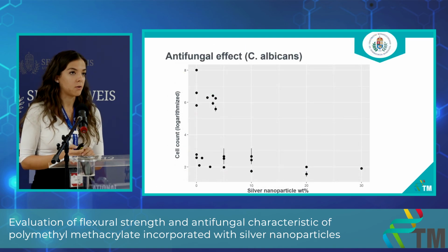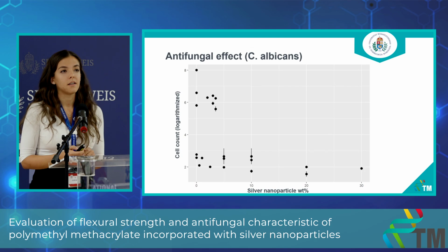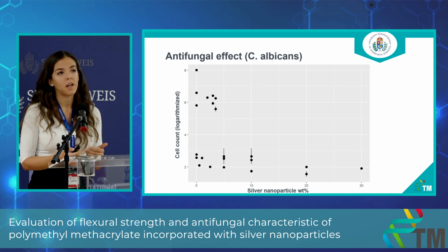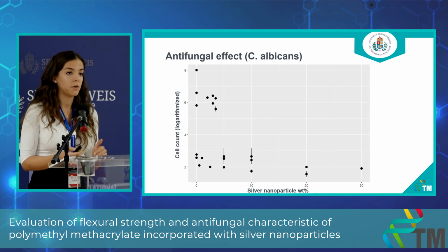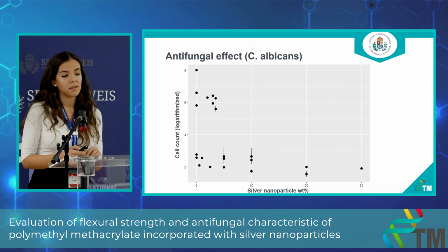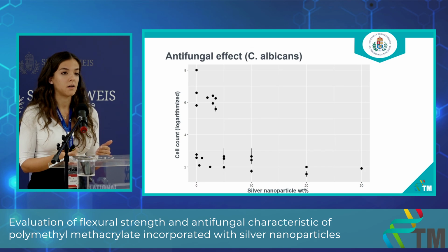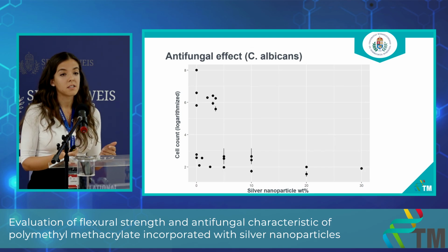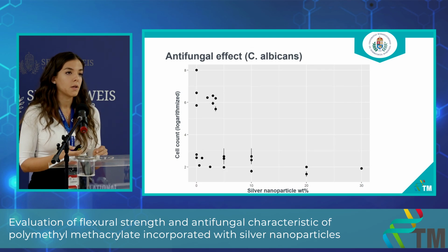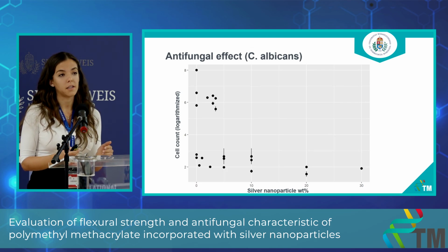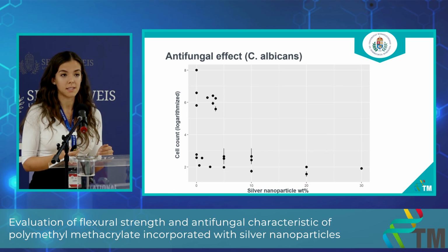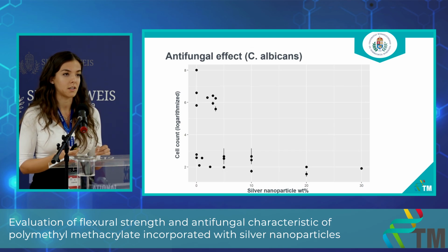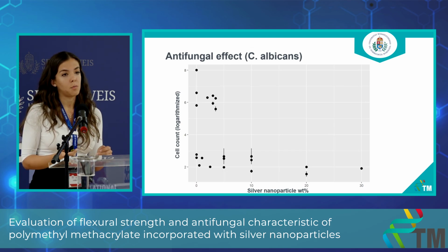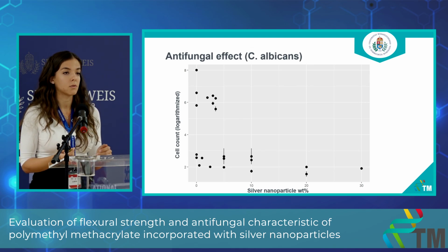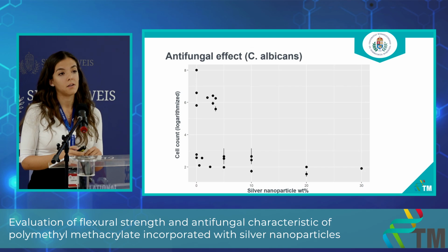Let's move on to the second outcome, which is the antifungal effect. The antifungal effect shows the number of the cells in the liquid around the samples, and it is caused by the dissolved silver ions. And on this graph you can see the cell count on the vertical axis in logarithmic scale, and on the horizontal axis you can see the silver nanoparticle concentration. And with the increasing silver nanoparticle concentration, the cell count was significantly decreased.